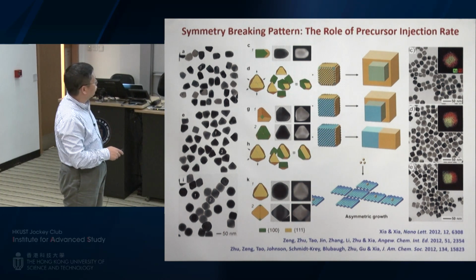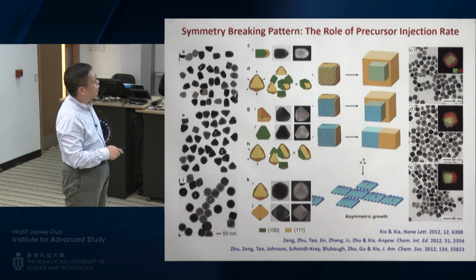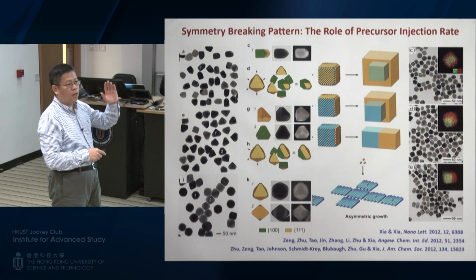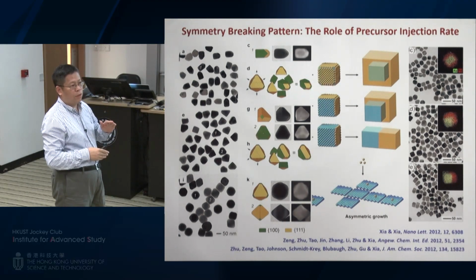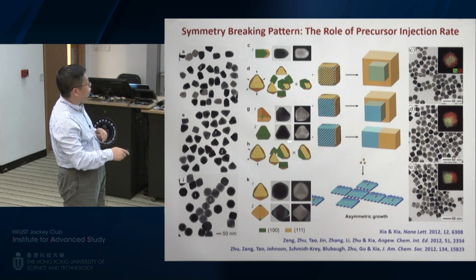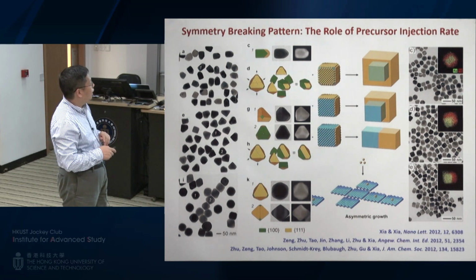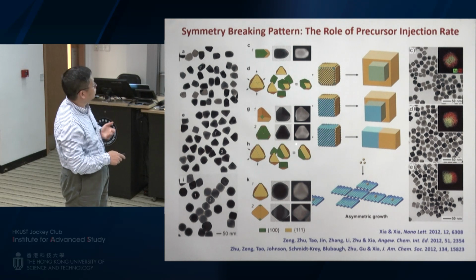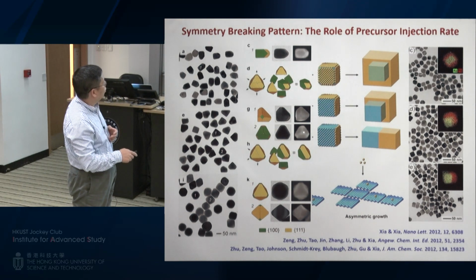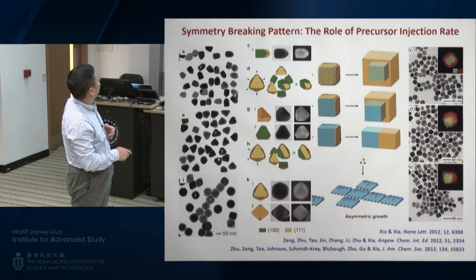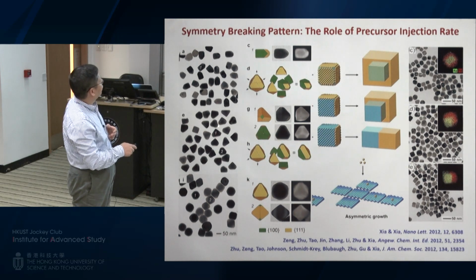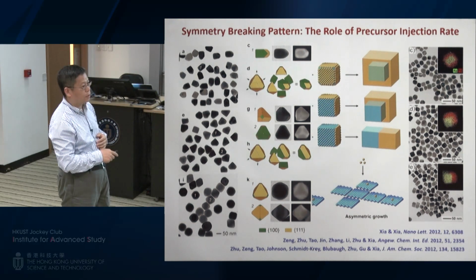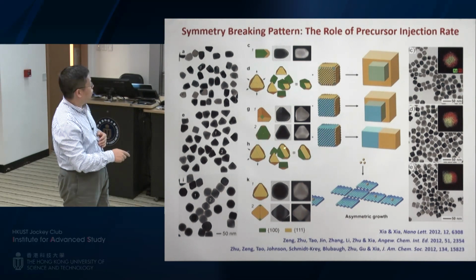Or you can have growth on 3 of the 6 side faces. So the final product is going to be something like this. We call this a semi-truncated octahedron. You take an octahedron, you truncate off 3 of the corners. The other 3 left will basically give you this very special shape. And this shape, depending on how they are oriented on the surface, may give you a triangular projection under TEM. There's one over here. Or it may give you what we call the house projection. So those are other different orientations. Okay, so that's basically the structure, this piece over here.